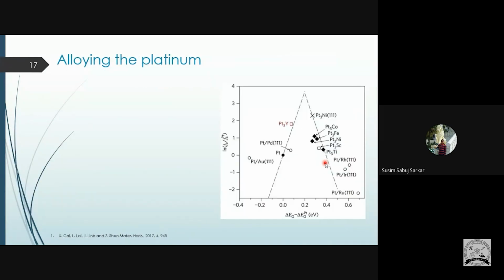So another thing is that people are trying alloying the platinum. People are trying polycrystalline platinum nickel or platinum cobalt electrodes. This has enhanced the activity of pure platinum. In the same volcano plot, there is the ratio of the specific activity here, and the other axis is the difference in oxygen adsorption energy. There you can see platinum is 0, 0 because it is pure platinum. Now people are mixing platinum with other alloying metals to see what will happen.